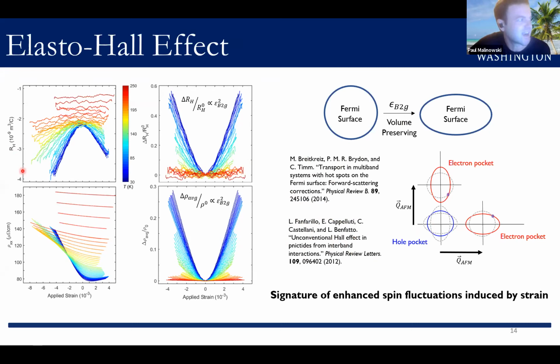this would suggest that the carrier density is changing by a lot, like even in a single band model, I assume. But even in a multi-band situation, this giant change is not very easily explainable. The numbers don't seem to suggest that you could change the magnitude of this by this amount. So that's kind of what motivated us to look at these sorts of ideas, where they directly show that this sort of change can occur.